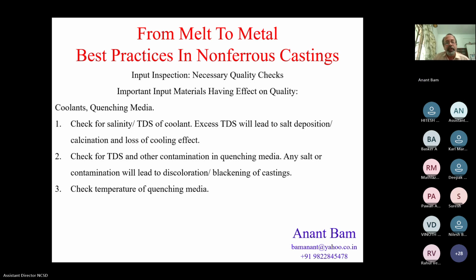Again, any salt or contamination in the quenching media will lead to discoloration or blackening of the casting after heat treatment. And once the casting blackens during quenching, it is very difficult to get back its own white luster. So you have to be very careful. You have to use preferably demineralized or DM water for quenching media as well as in the cooling lines.